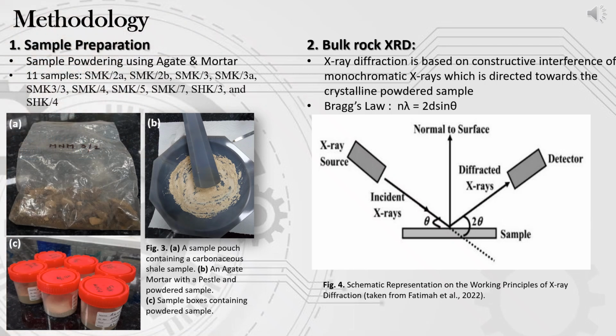The methodology of the dissertation includes two important geochemical tests: X-ray diffraction and inductively coupled plasma optical emission spectroscopy. Before starting with the tests, sample preparation is the most crucial step. 11 samples were finely ground and powdered using an agate mortar and pestle. Contamination was checked by cleaning the agate mortar before and after using it for powdering.